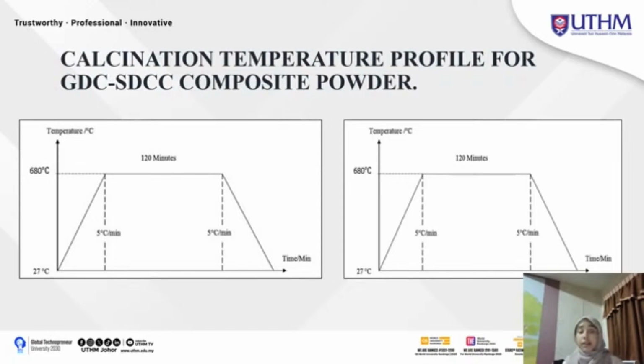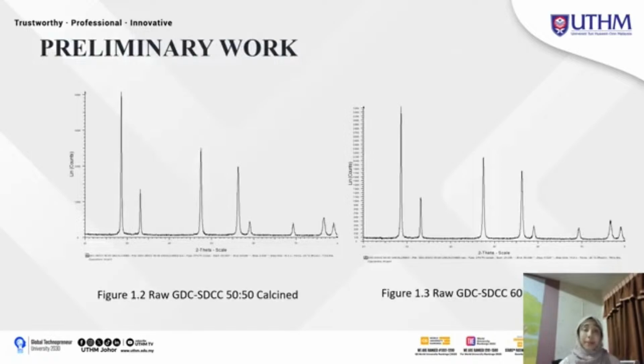So from 27 degrees Celsius, it will go upwards for some amount of time. And then for the second one that is plotted here, it shows that it will be constant for 120 minutes at 680 degrees Celsius, and then it will go downwards until it meets the 27 degrees Celsius temperature again. So here's a bit about my preliminary work that I have already gone through for this project so far.